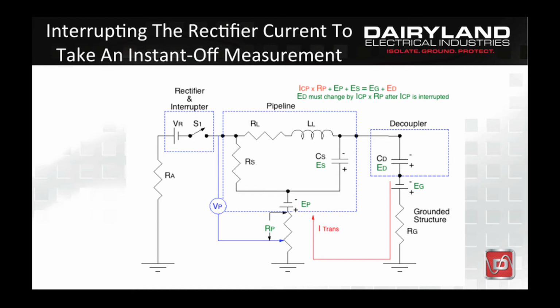When the rectifier current is interrupted to take an off potential measurement, one would expect the pipeline voltage to decrease in value because the IR voltage drop component, highlighted in orange in the left side of the equation, was eliminated. However, since each side of the equation must always be equal, this means that the voltage across the decoupler capacitor, represented by E sub D, must then change exactly by the value of the IR drop component that was eliminated by turning off the rectifier current. The voltage across the decoupler is the only element in the right leg of the circuit that can change in voltage to keep the voltage across the two legs of the circuit equal, since the corrosion potential of the grounding conductor, E sub G, is fixed in value.